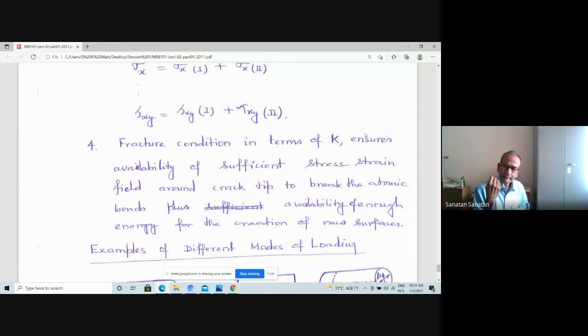So fracture in terms of K ensures both necessary and sufficient conditions, but in the case of energy-based criterion, it does not ensure both conditions, and therefore they are actually lacking. But then K condition is actually necessary and sufficient. So that's why K is a much stronger criterion than the G-based criterion.